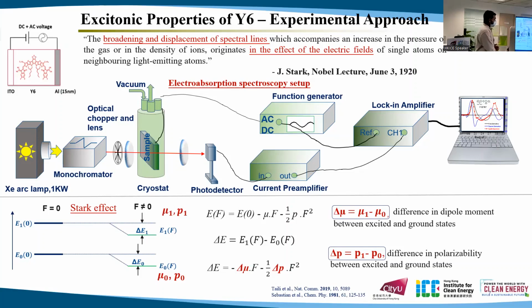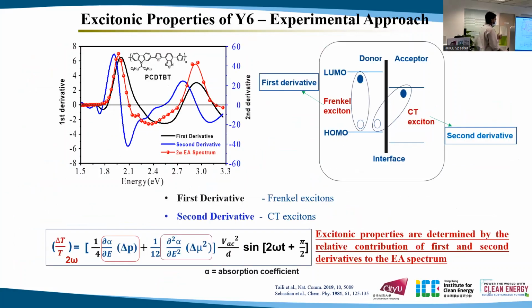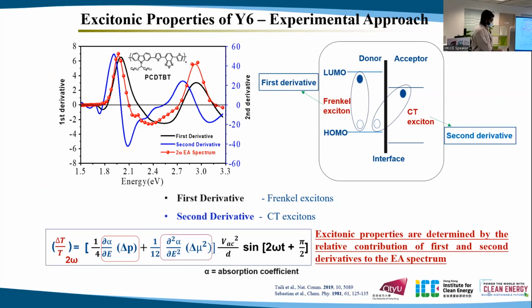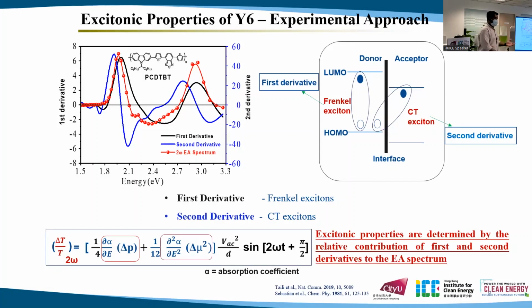And in this figure, you can see when we apply an electric field, the energy state will shift by a parameter delta E under the electric field, which depends on the change in dipole moment and change in polarizability between the excited and the ground states. And this is an example of EA spectroscopy we did on PCDTBT, the conjugated polymer. And how to analyze the signal? If the EA spectra match with the first derivative of the device absorbance, that indicates that it is more Frenkel excitons. And if it is the second derivative, then that means they are more CT type, like CT excitons.